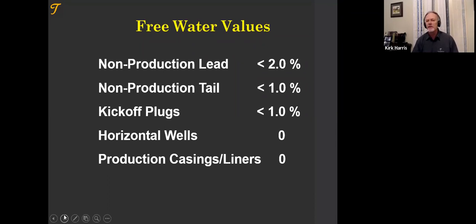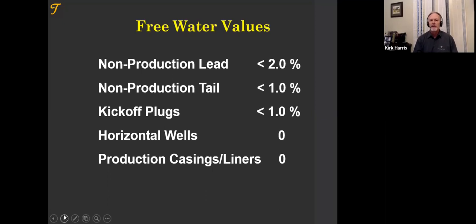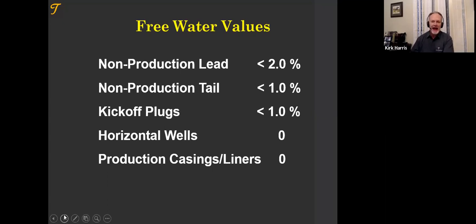Someone asked: if you're in the field, how far off can you be on your density and still have zero free water? An expert in a prior webinar said — obviously dependent on slurry — you could be off by up to 0.4 to 0.5 ppg and slurries still had zero free water. But it does show how important it is to mix correctly on location. We'll be talking about continuous mixing and batch mixing on February 17th when we discuss pumping cement operations.